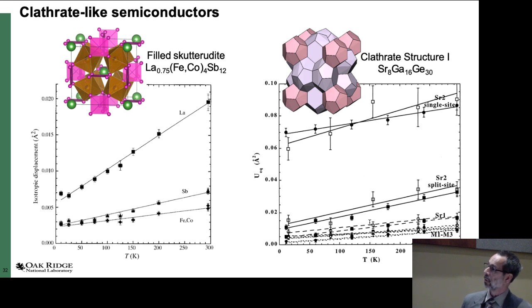So you can see here the lanthanum, which is the heaviest element in this structure, which would, if all was not anomalous, would be down here, has a very large displacement and a large intercept. Same for the strontium-2 in this large cage. These are 2 sets of data, both single crystal and powder. These were all collected at the HFIR. Even if you use a split site model for the strontium-2, which shifts the curves down to here, they're still anomalously large. So we think of the caged atom as rattling in the cage, which is kind of an exaggeration.